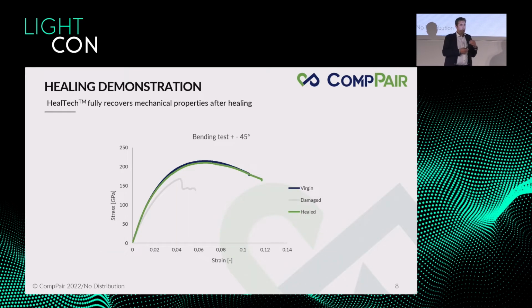We have seen before some demonstrations visually with impact that you see with the demonstration that we have on the booth as well, but how does it stand also mechanically? And this is what is important as well. This is a typical test that we like to have and that we propose as well to our customers to show the damage. And coming from also the self-healing field and for many years of research, when we are providing self-healing strategies to composites, we cannot reach the fibers. If we reach the fibers, we are not repairing them.